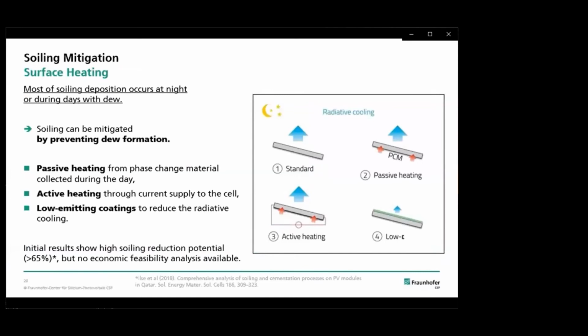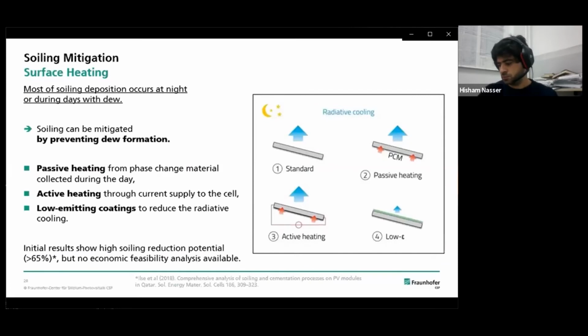Further mitigation strategy could be surface heating. And since most of the soiling deposition occurs during the night and also is correlated to dew formation, which happens also mostly during night and early morning hours, soiling can be mitigated by preventing the dew formation. And for that, we can use different concepts like passive heating, for example, using phase change materials, also active heating, or